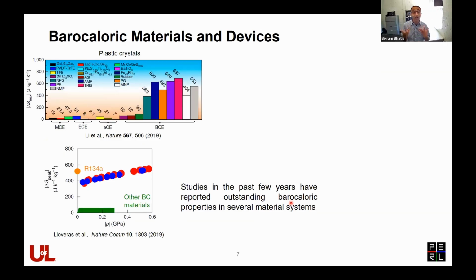So what caused a rise in interest in this field, the field of barocaloric heat pumps and coolers, is the study that came out in 2019, which showed what is known as a colossal barocaloric response in plastic crystals. These are materials that have order disorder phase transition, which result in really large latent heats, which are shown here. The entropy changes associated with that order disorder phase transition can be really large. It's by far the highest among all the other caloric phenomena tested. And what was interesting was, for the first time, we were getting entropy changes that were on par with traditional refrigerants like R134A. And so that is what caused that excitement. But again, there are a lot of challenges going from this material to an actual device.